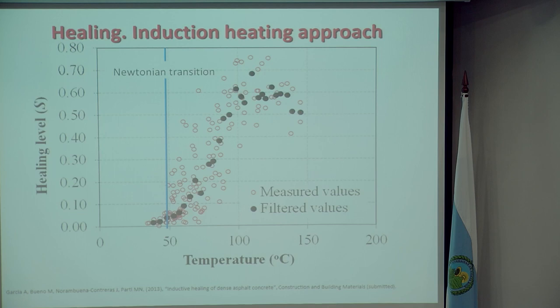And once you've done that, you can get a whole range of different healing ratios. The healing ratios go up to as high as about 75%. So this is not a complete healing. We're not able to restore the properties to what they were initially, but we're able to get them back to at least 75% of their starting point. The two sets of data there, the red unfilled circles are the measured data, and then we've done some statistical filtering of the data to give you your black curves or your black circles.